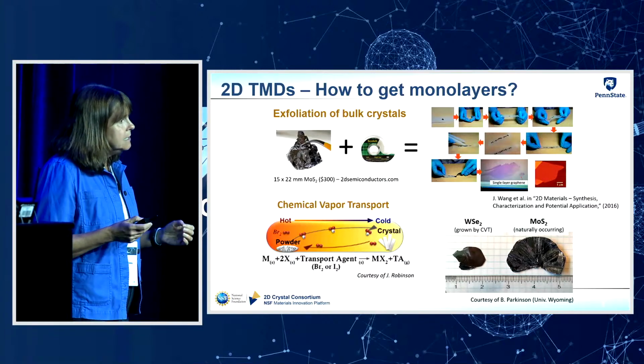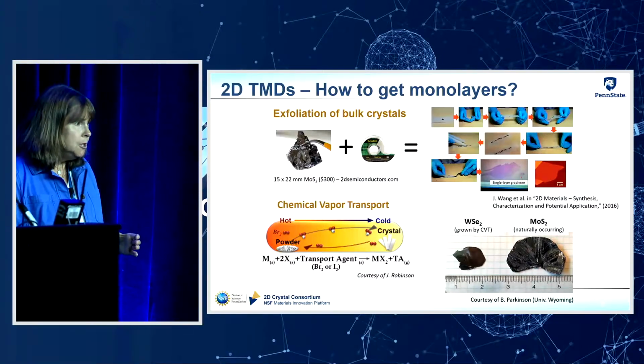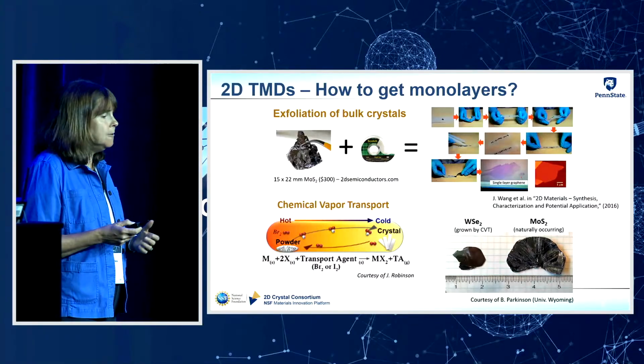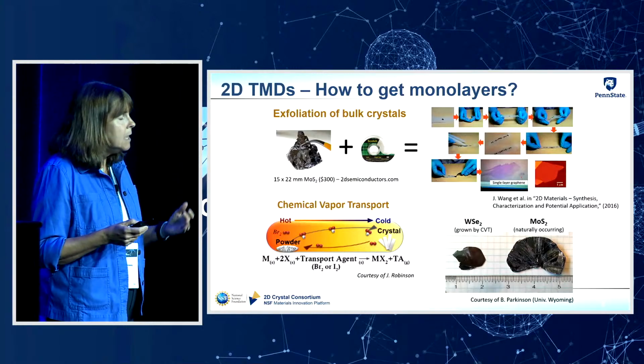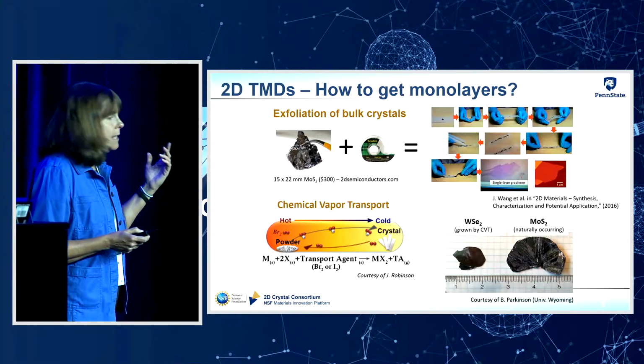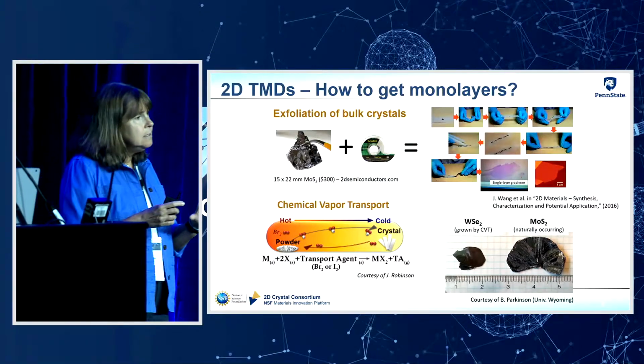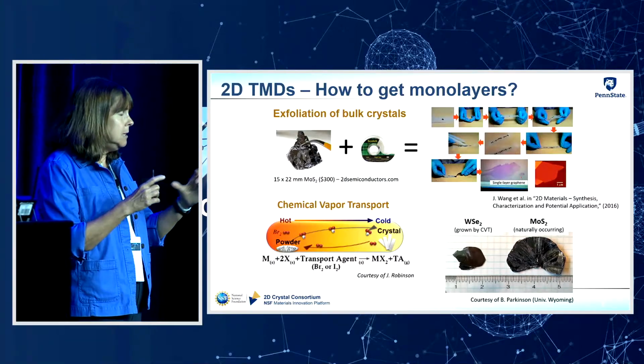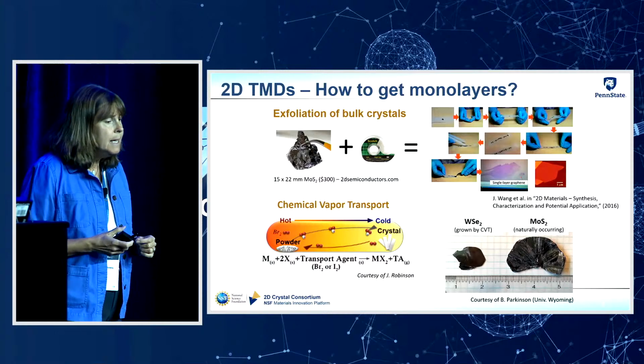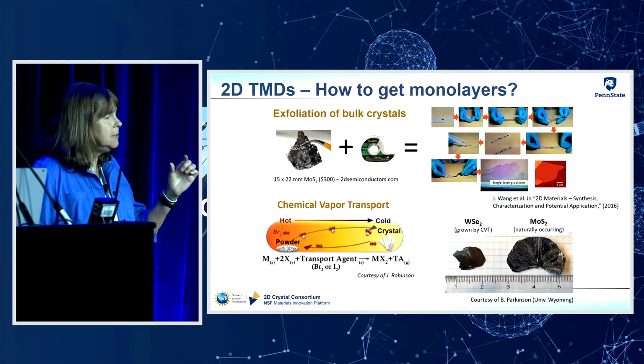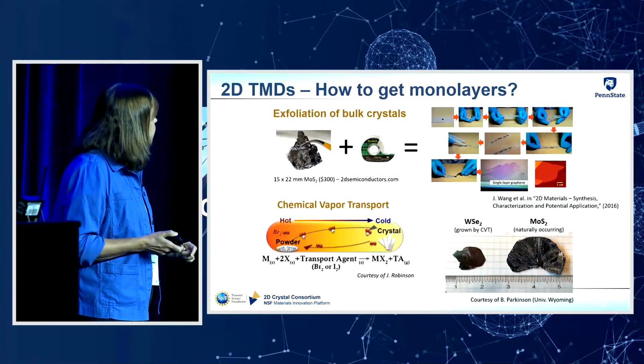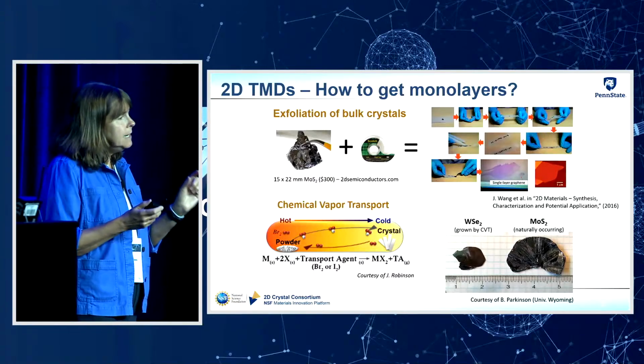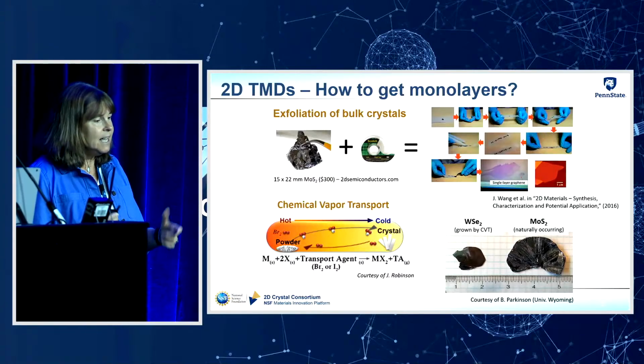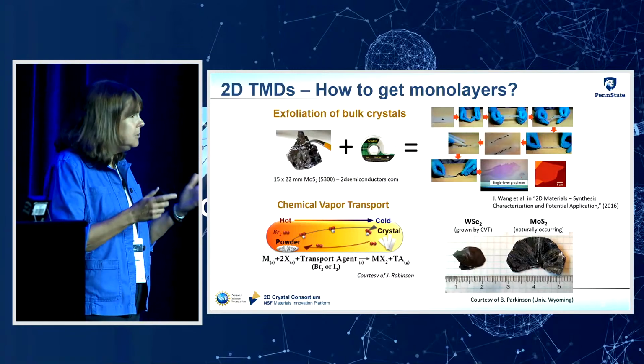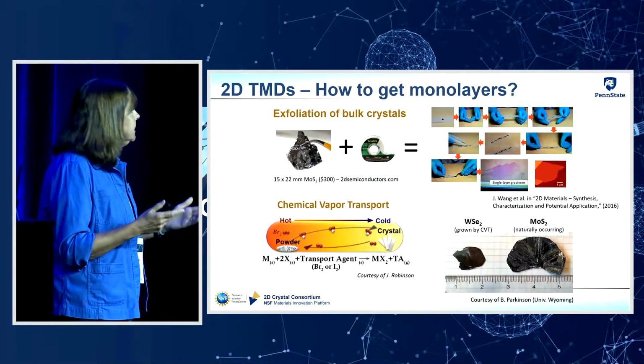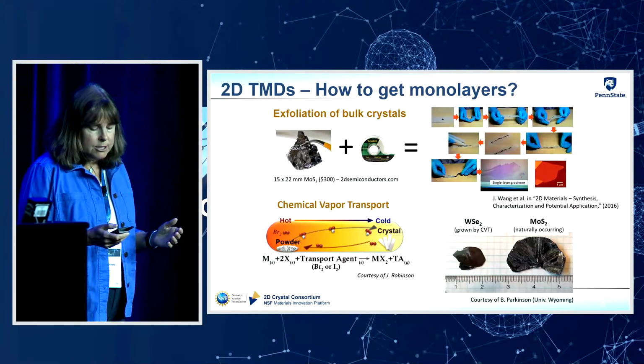And the reason for that is it's very difficult to make large bulk crystals of something like moly disulfide or tungsten diselenide. The technique that's most commonly used is chemical vapor transport. This is a synthesis process that's carried out in a sealed quartz tube. And typically the sizes of the crystals that you can get from chemical vapor transport might be on the order of 1 inch, maybe 2 inch in size, as I'm showing here. But they're irregularly shaped, and they're really not viable for a device technology.